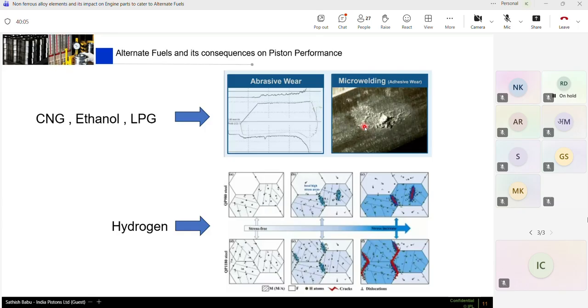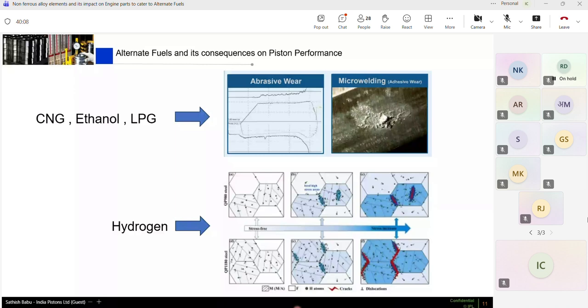Of course, I told you about the hydrogen, quick sketches about a normal intermetallic phases of our microstructure. Because of the very high hydrogen fuel pressure release and heat release rate, there are chances of pitting marks created on the parts, which can slightly make your aluminum alloy brittle, and aluminum alloy becoming brittle is very rare to see. This slight brittleness will open the intermetallic phases and allow the hydrogen to freely go inside and create an embrittlement situation, which makes a fatigue crack over a period of time, which is not a good scenario for an aluminum alloy piston running in an engine.